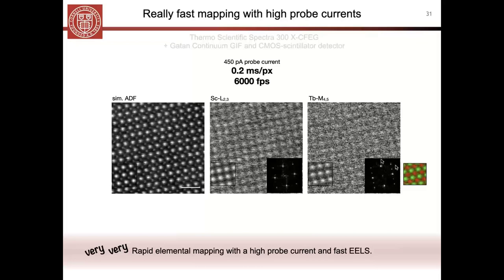When you compare the FFT of the terbium map to the scandium map, you can look back at the atomic model of the material, and you can see exactly that. In the terbium map, you have these superlattice peaks here, which relate to this left-right ordering of the terbium atoms in the unit cell. So again, you can see that in the model, you can see it in the ADF image, and you can in fact even see it in the terbium EELS map, and again, preserved spatially or in reciprocal space in the FFT. If you look at scandium, you can see that we actually don't have those peaks, and that's because the scandium sublattice doesn't have those left-right distortions, and so in this case, there's no scandium superlattice.